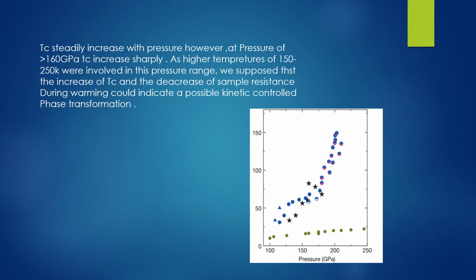However, at a pressure of 160 gigapascal, Tc increased sharply. As higher temperatures of 150 to 250 Kelvin were involved in this pressure range, we supposed that the increase of Tc and the decrease of sample resistance during warming could indicate a possible kinetically controlled phase transformation. This graph explains all these things in the result.